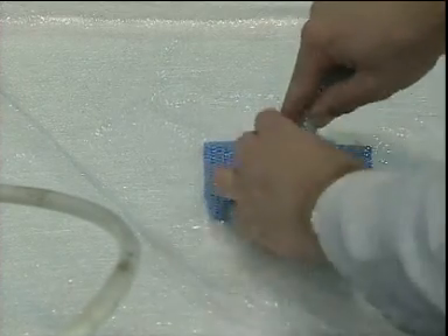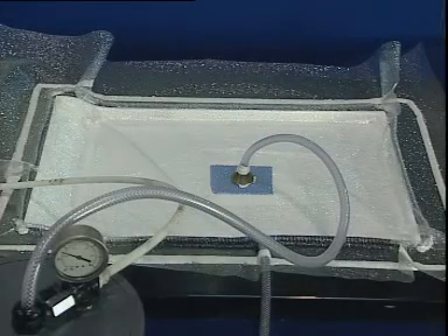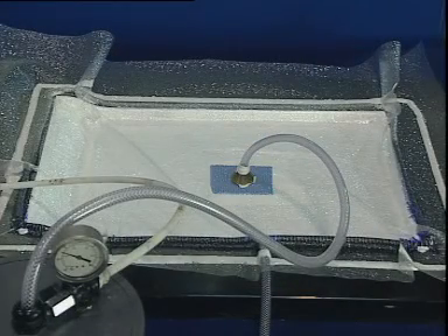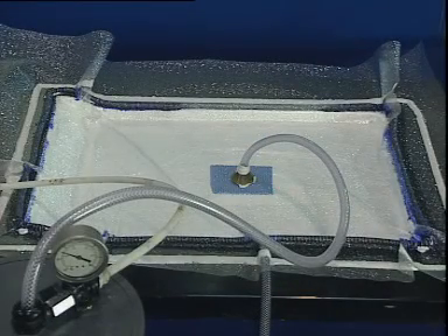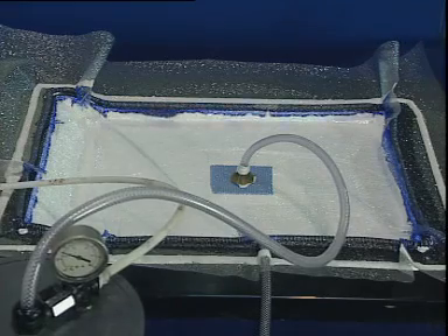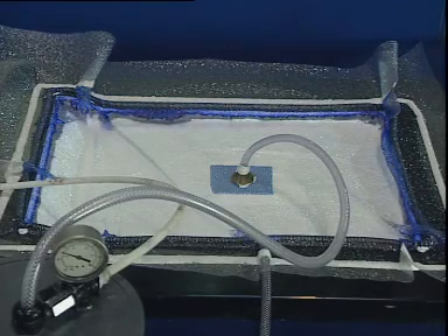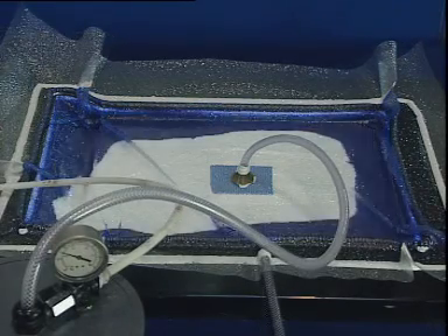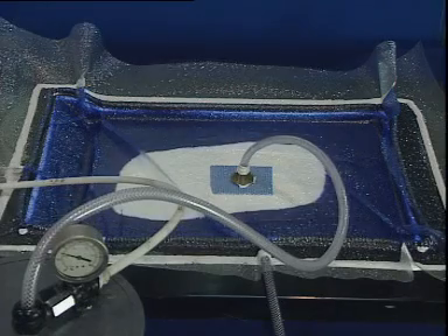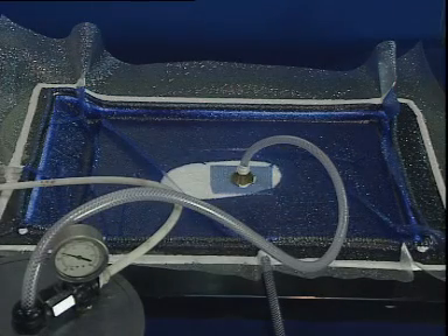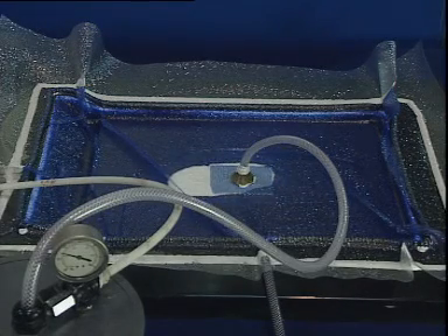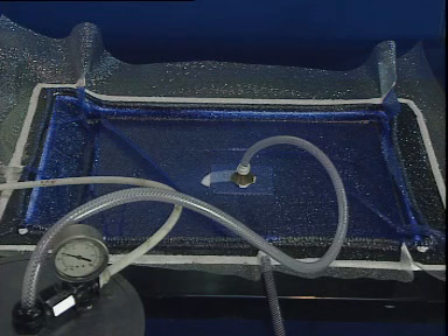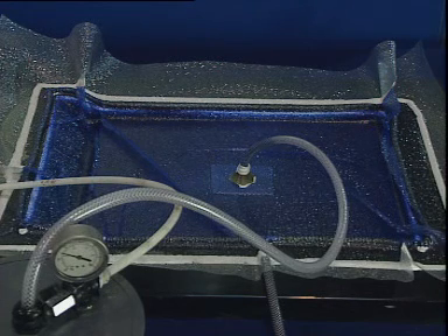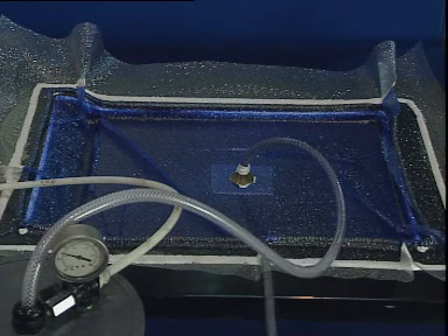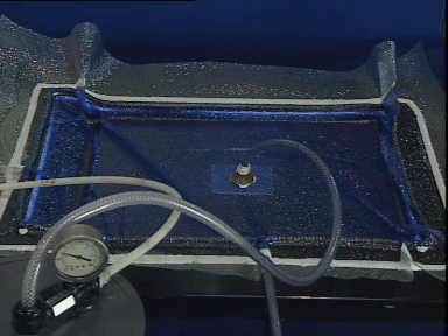Resin is fed from the outside tube into the peripheral channel with a vacuum of between 0.6 and 0.8 bar being pulled from the central point. This method has the advantage of quicker fill times, but the disadvantage of a greater risk of drawing air across the laminate if the bag is not sealed properly. An alternative is to feed the resin via the central hose connection and pull the vacuum from the outer channel.